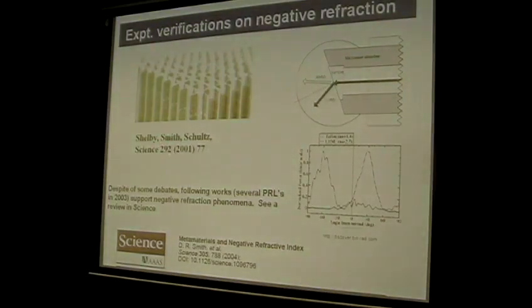After the proposal of John Pendry, the UCSD group fabricated this very famous negative index material sample, and they demonstrated that this sample indeed possesses a negative index. This is the wedge sample that they fabricated, and they shine an EM wave, actually a microwave, onto the sample. If the system possesses a positive index, the refracted wave will go like this. And if the system possesses a negative index, the refracted wave will go like this. That is the experiment. Indeed, for the positive one they have positive refraction, and for this material they have a negative refraction.